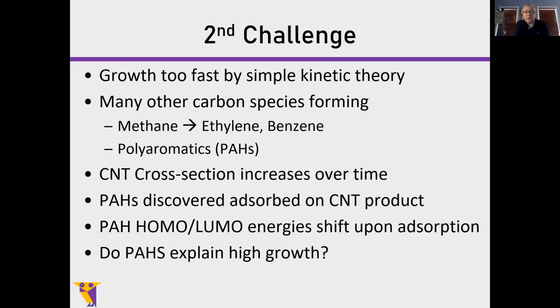So this gets to the second challenge. Right now, what I see in the reactors I work with, the growth is too fast to be explained by simple kinetics. Other carbon species are forming. Methane is well known to pyrolyze into ethylene, benzene, other things, and to polyaromatics. As the CNT grows, its cross-section is increasing over time. It's getting bigger. So if the cross-section is getting bigger, maybe that's explaining why I'm seeing an increasing growth. The PAHs are there. Their HOMO-LUMO energy shifts are proven experimentally and theoretically. Do the PAHs explain the higher growth? I don't know. But if they do, it would mean a drastic change in what is used to make nanotubes. Coal tar and other bad chemicals could be used to make them.